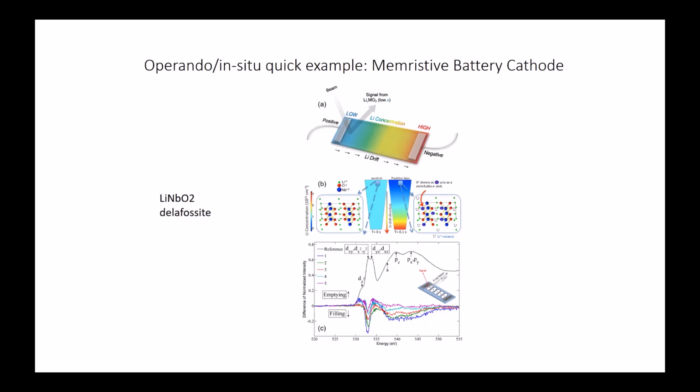I was curious, when you're doing the soft X-ray measurements on the battery materials, do you have any problems with self-absorption, and do you need to use inverse partial fluorescence yield? There's going to be self-absorption if you use fluorescence yield, because the amount of the transition metal is significant. Since we were essentially looking for, and also for the oxygen, that would be the case. Since we were looking for qualitative changes, we were not too concerned about it at the moment. If we were trying to quantify things, then I guess we'd have to take further steps to address the self-absorption issue. Okay, thank you.